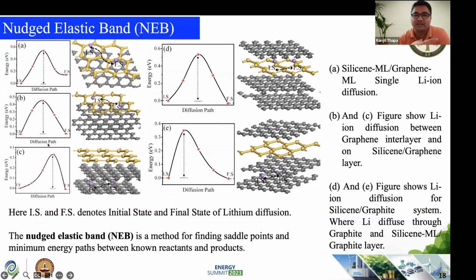How the lithium should go inside? So in that case, you can see easily that if lithium is inside the carbon, the diffusion energy barrier is around 0.3. But if it is going in between silicon and carbon, the diffusion increase to 0.5 or 0.6 electron volt. So that means you need to quantify what is the reason, and all the reason is because of your localized pi of silicon and delocalized pi of carbon. And we have really matched all these results, and we have shown how much percentage of your silicon should be there, so that it can be easy for you to maintain such heterostructure for your anode material.